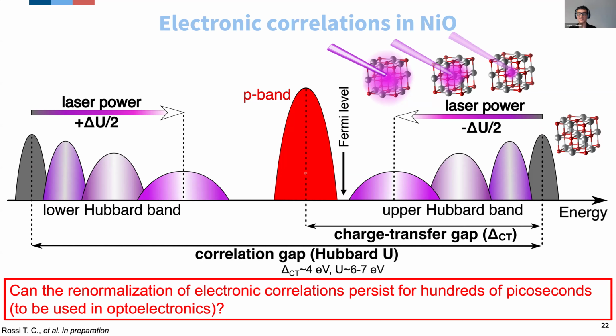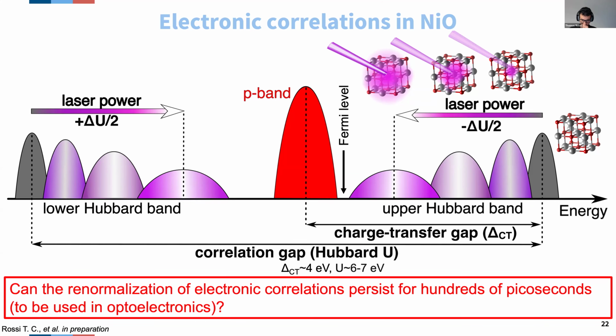The problem is that it would be interesting to know for how long this renormalization of the correlation gap can live. Especially for applications, you would like this renormalization to live for at least hundreds of picoseconds such that it can become usable. And this is typically why we did the pump probe X-ray absorption spectroscopy experiment on nickel oxide at the nickel K edge to see if we can capture this renormalization of electronic correlations and for how long it lives.